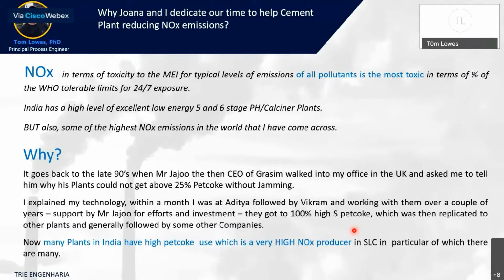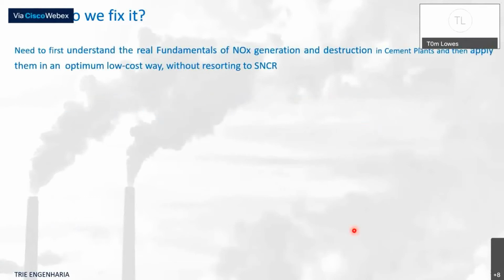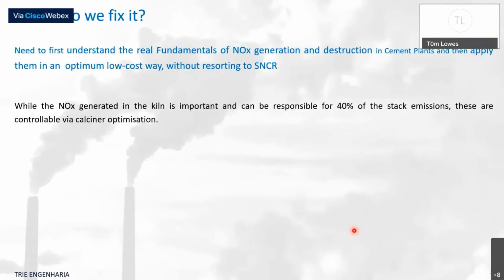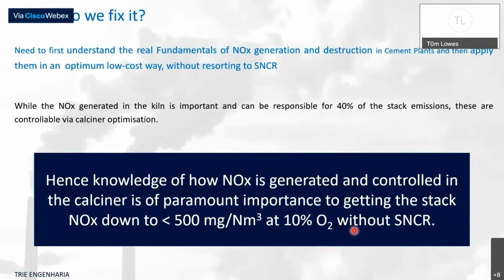They got to 100% high sulfur Petcoke, which was then replicated to other plants and generally followed by some other companies. Many plants in India have high Petcoke use, which is a very high NOx producer, particularly in separate line calciners, of which there are many. So how do we fix it? Typically, you need first to understand the real fundamentals of NOx generation and destruction in cement plants, and then apply them in an optimum low-cost way without resorting to SNCR. While the NOx generated in the kiln is responsible for up to 40% of the stack emissions, these are readily controllable via calciner optimization. Hence, knowledge of how NOx is generated and controlled in the calciner is of paramount importance to getting the stack NOx down to less than 500 at the stack without SNCR.